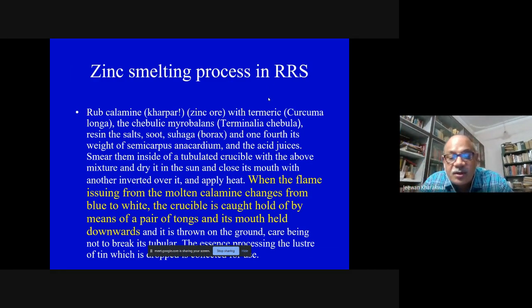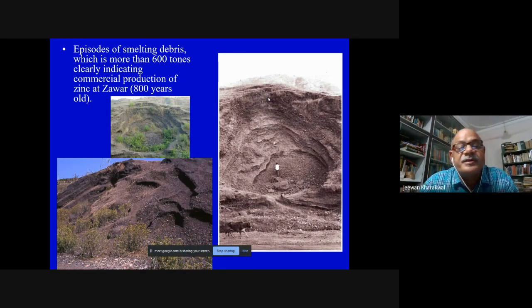So the crucible is caught hold by means of a pair of tongs, but in that case, the pipe was not broken. That is very important. That means in the pipe, there must be the essence of zinc. Therefore, they avoided breaking the nozzle part of the retort. The other part of it, they did not care for.